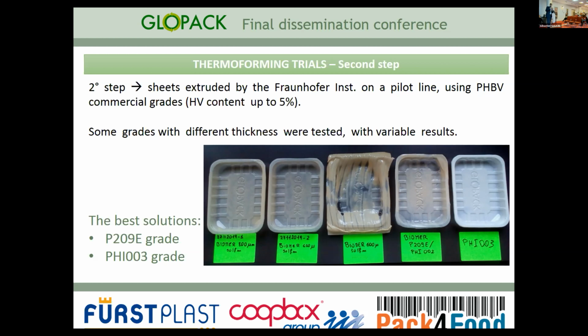The color is slightly different, but the final result was quite good. These grades have different content of HV, from 0 to 5. You can see that it was not so easy to find the right parameters and also the right composition to have a good final solution on tray.